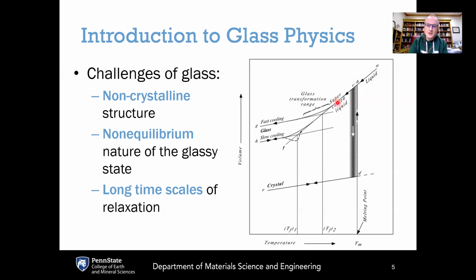So the supercooled liquid is stable on its own, but if you were to take this and either wait long enough time or heat it up into this shaded region where it is more likely to crystallize, then it would undergo this first order phase transition and then crystallize. Now, that's a supercooled liquid. How do we get a glass?